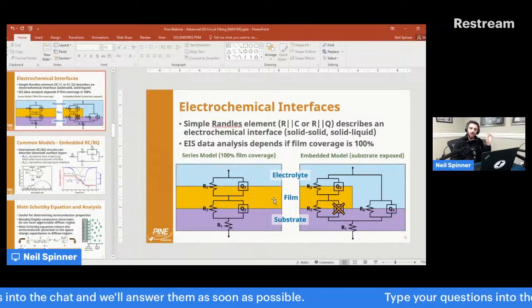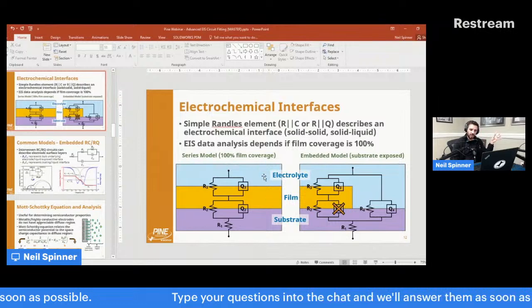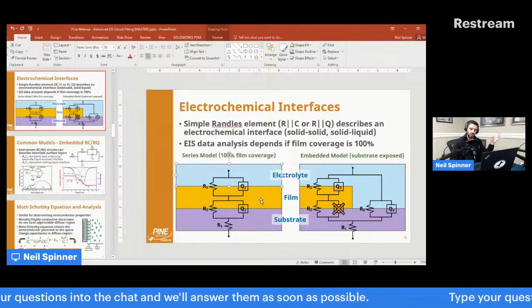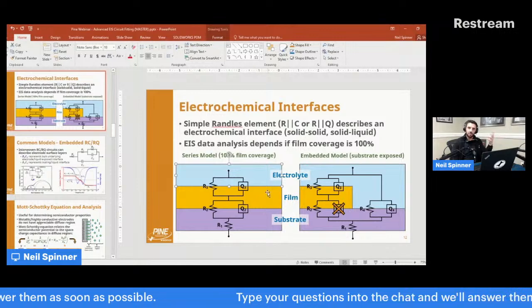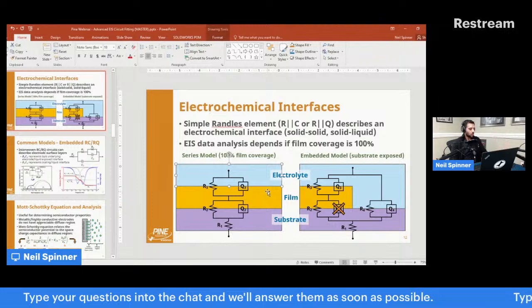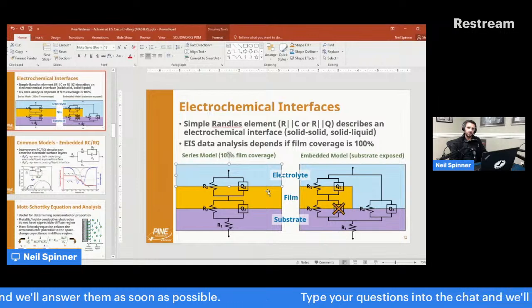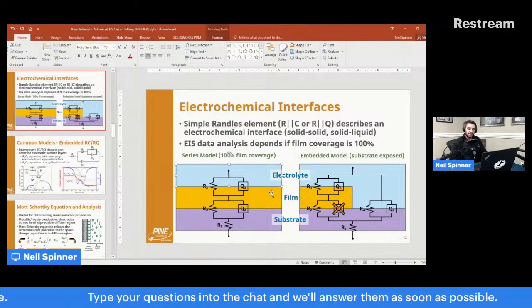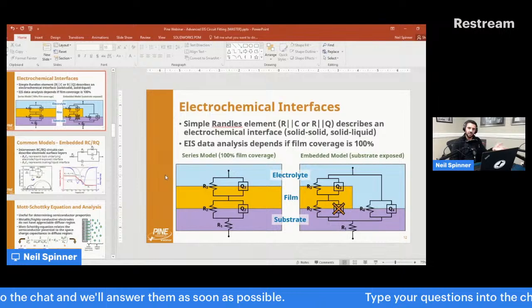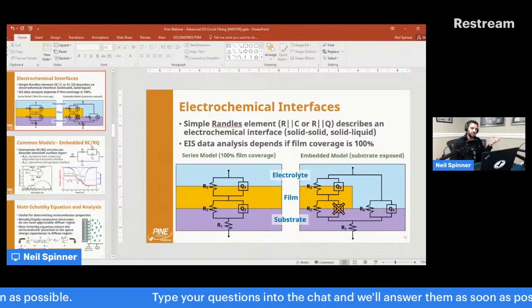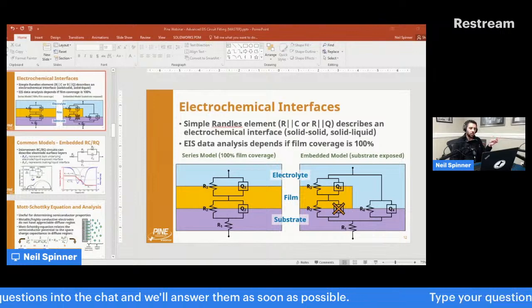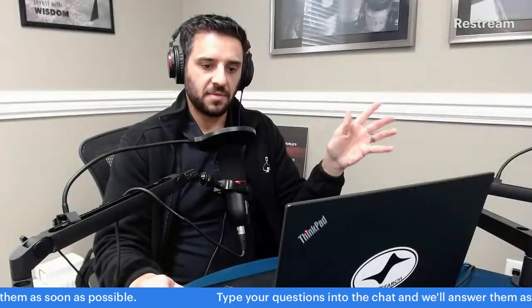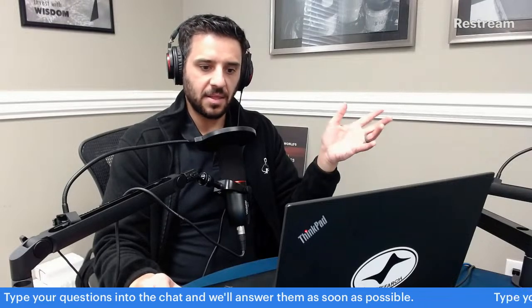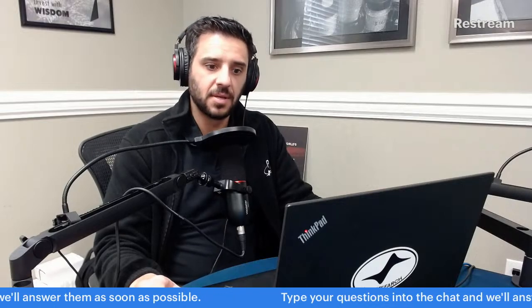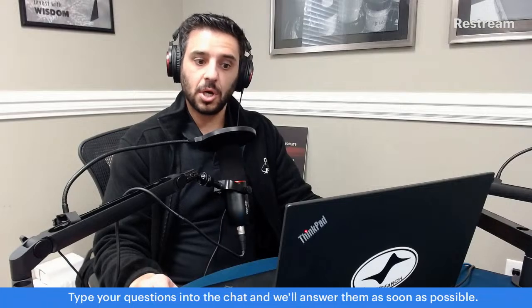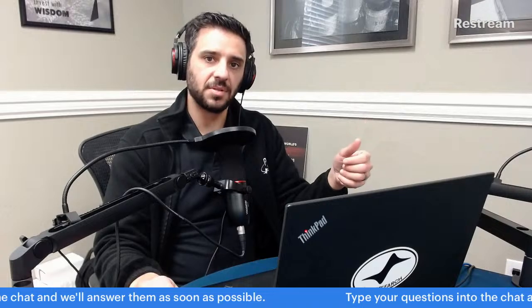That's relatively unaffected. But you are going to change the Faradaic reactions that are happening at your electrolyte, at your film or at your substrate even, or the amount of double layer capacitance could change because it's a liquid-solid interface. So oftentimes by changing the potential, you can sometimes elucidate whether that's the case. Now, the other way to tell is whether you have microscopy, or some kind of in situ or ex situ analysis of your metal and your polymer. If you're able to do something like that, you might be able to tell whether part of your substrate film has porosity or not. And in the case that you can determine that, you might be able to successfully figure out which of those models is most appropriate.